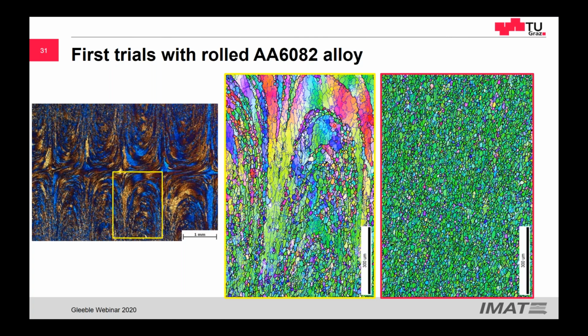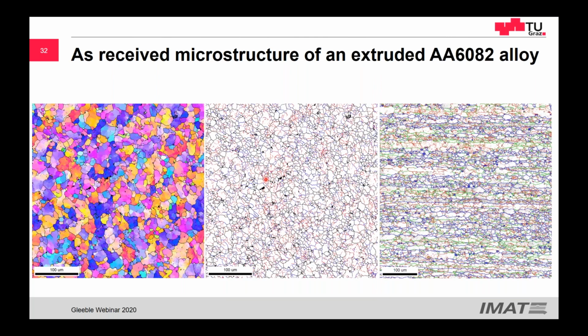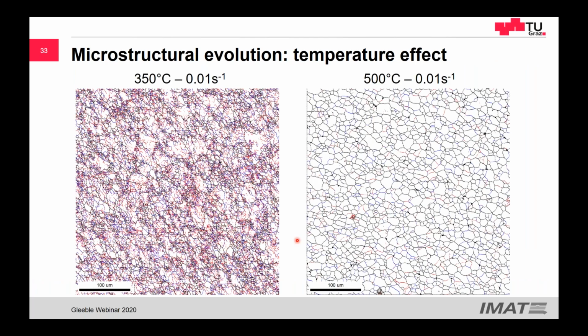So we changed the material into extruded material that looks, in the extrusion direction, like the right picture here. So here you can see in blue the high angle grain boundaries of the as-received material with very fine grains, and this is the transversal direction. So we said, okay, what happens now if we do torsion here? And if we do torsion here, we got something like this.